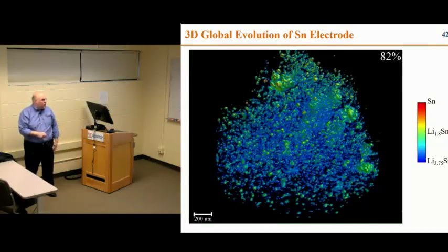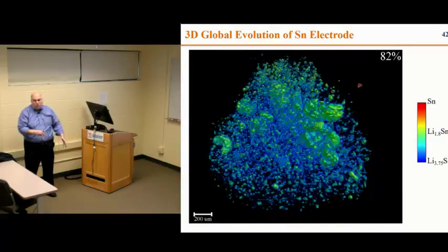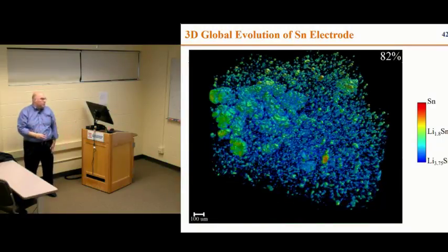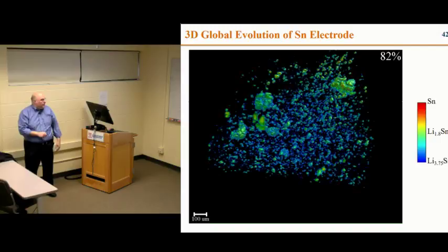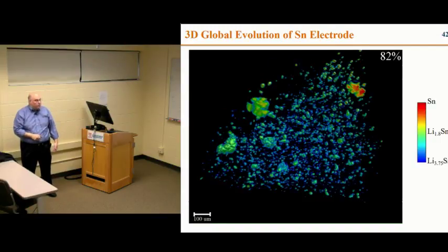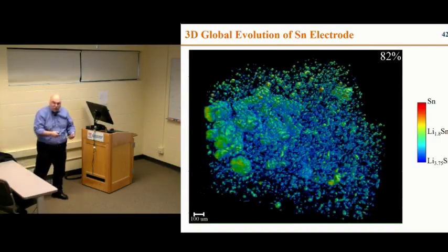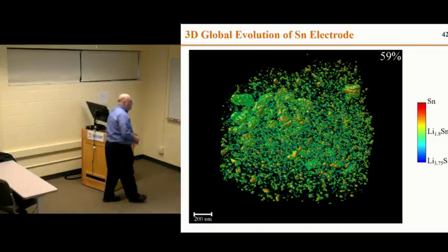This is almost fully lithiated. And you can already see these particles. Number one, they've grown enormously. And number two, they're starting to break up, right? And the nice thing is we can actually see inside the particles as well, because this is an internal measurement. It's not just the surface of the particles that we're looking at.